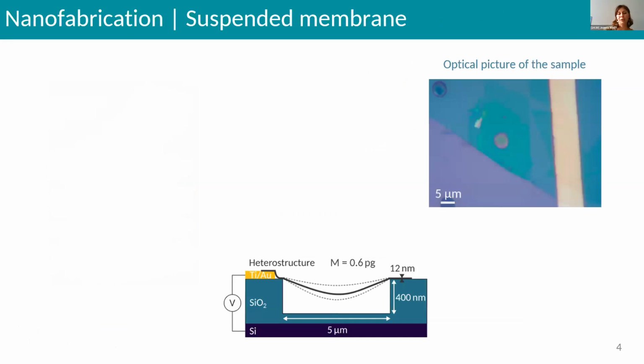So first, I will show you the samples we are using for these studies. So here, there is a scheme of a nanodrum. So you can see here the hole etched in a silicon substrate, the suspended heterostructure, and also an electrode that we use to impose a gate voltage between the substrate and the membrane to apply a force by capacitive effects. So here is an optical picture of the sample. You can see here the hole and here the electrode.